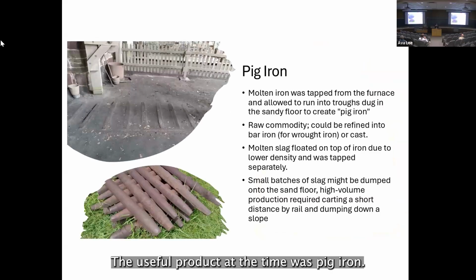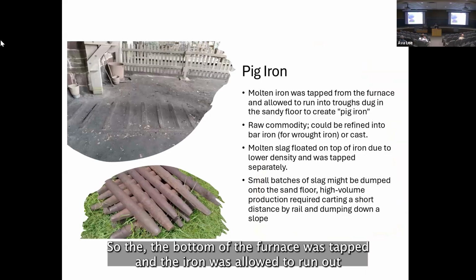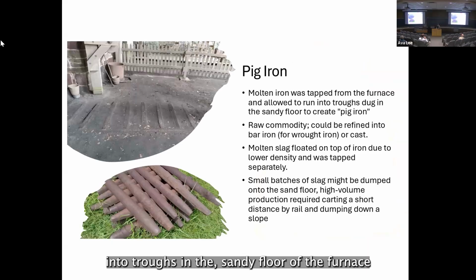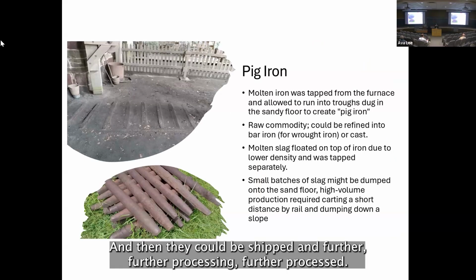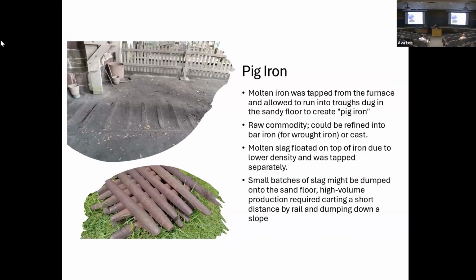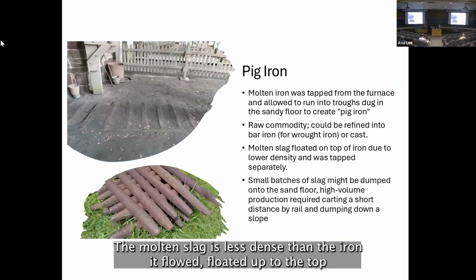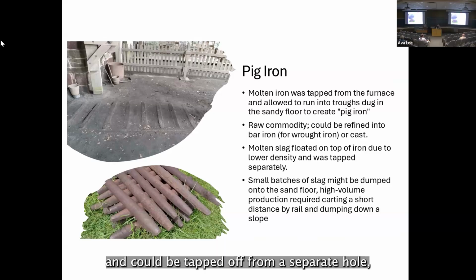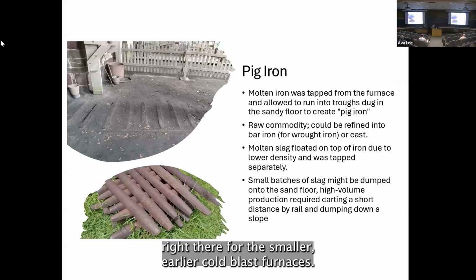The useful product at the time was pig iron. So the bottom of the furnace was tapped and the iron was allowed to run out into troughs in the sandy floor of the furnace that generates these iron pigs. That was the raw commodity, and then they could be shipped and further processed. The molten slag is less dense than the iron. It floated up to the top and could be tapped off from a separate hole, and then either poured out onto the floor right there for the smaller, earlier cold blast furnaces.